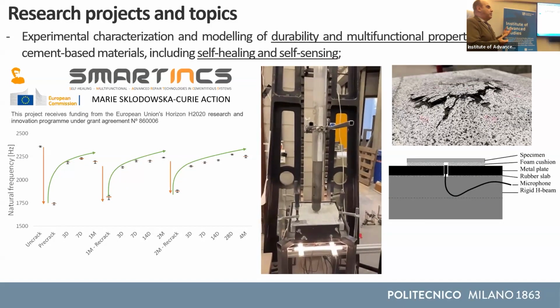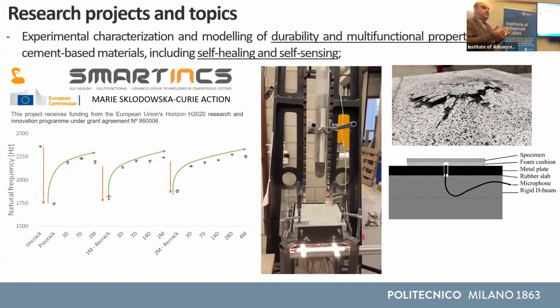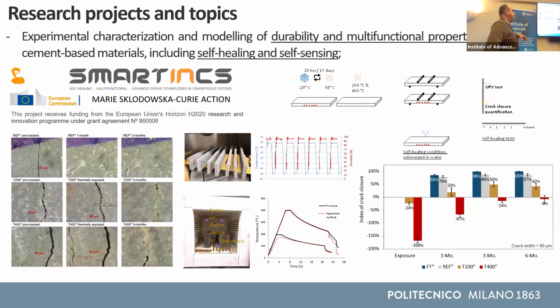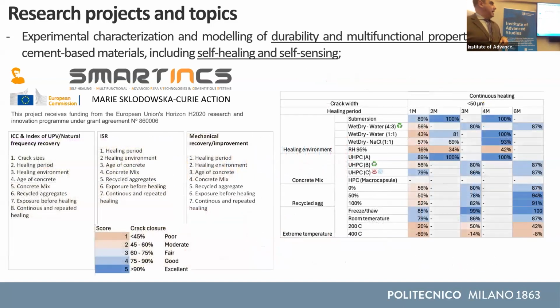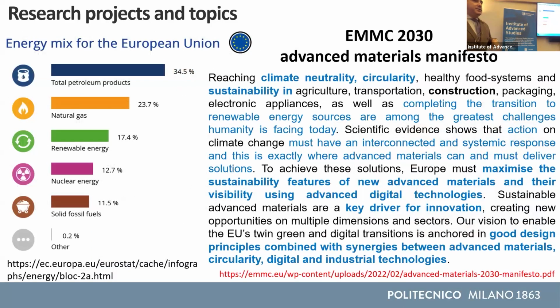For example, we investigated how these properties apply to impact, if you want to use for protective structures, how the material is able to recover its properties, how these materials survive higher temperature. This is particularly important if you go to nuclear containment, the secondary vessels, which can be subjected to up to 300 degrees constant temperature. It's high, but not extremely high. So the material still keeps its performance. We heated the material up to 200 degrees, these ones here, and we exposed it to high temperature. And after curing them for 3 months, the material was able to close back the crack. So it's able to survive with this activity. We investigated also freeze and thaw as well, and we try to come up with the design matrix to address the choice of the best material for the best application.